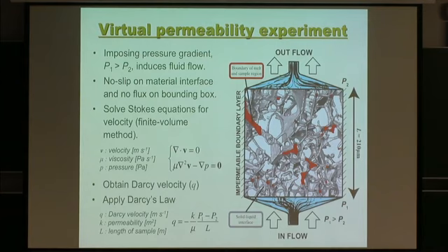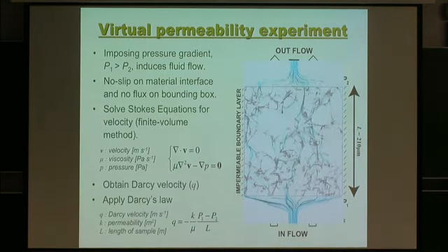So if you want to distribute that without the edge effect, you just add 2 layers of elements, all right? Then they distribute. And then with the pressure high at this end and low at that end, you're going to drive the flow. And with that driven flow, you can actually calculate the flow velocity.